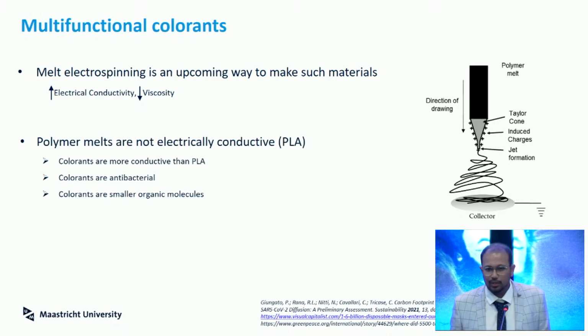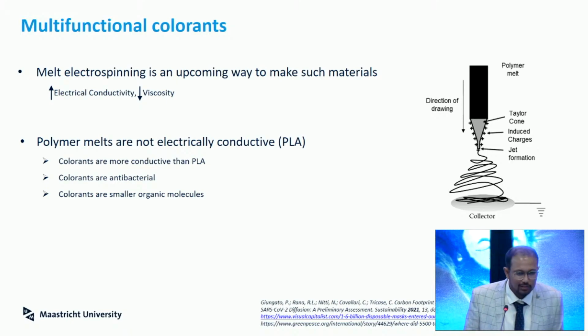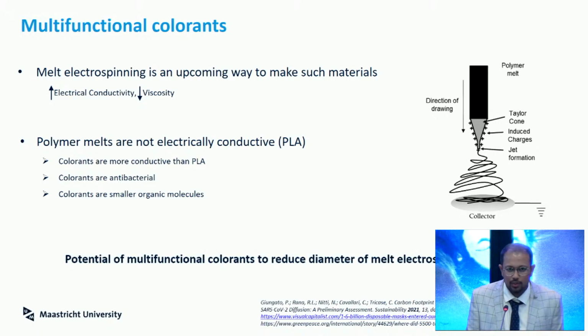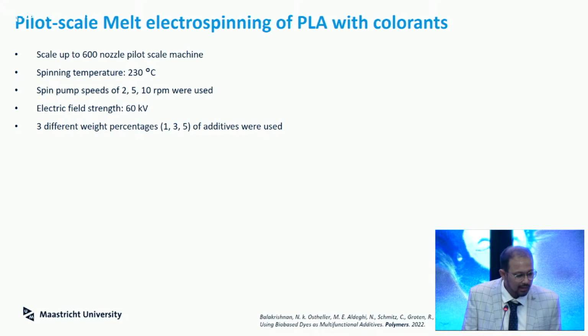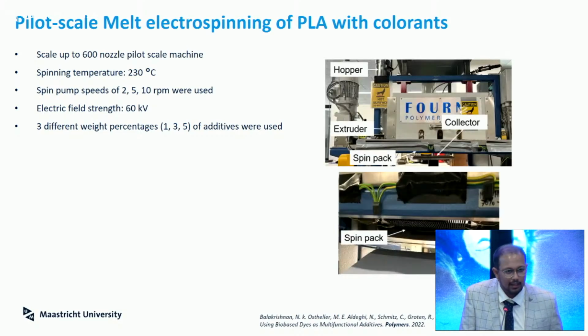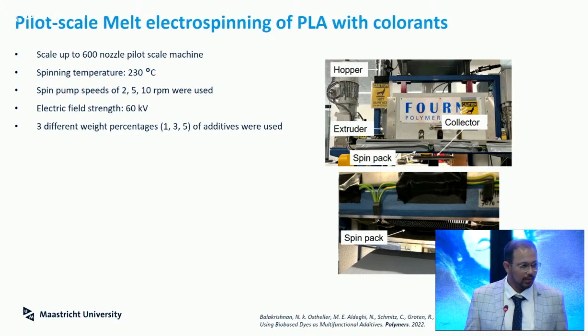And the idea was, why don't we mix these two? Of course, for masks, antibacterial is always good. So the idea was to check how these colorants work in this environment. That was the start of the second part of my thesis, and this is what I did for the second half of the thesis. We had a pilot-scale electrospinning machine in-house, which has 600 nozzles. I performed trials with various colorants first, a small proof-of-concept test to see whether it actually works the way I want it to. Then I measured the diameters and saw it was actually working.